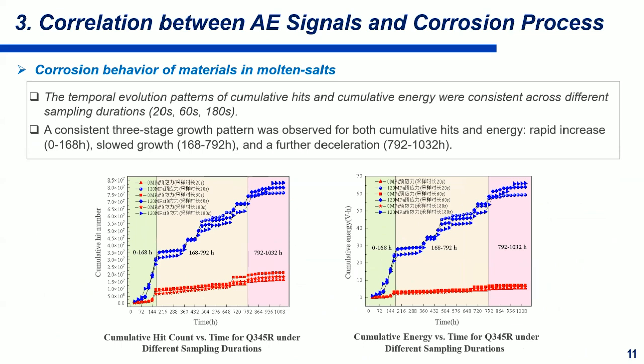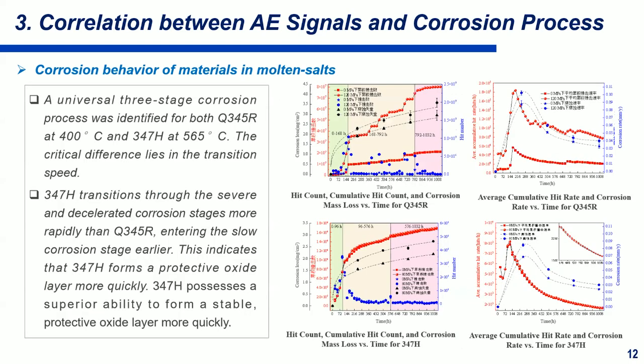The temporal evolution patterns of cumulative hits and cumulative energy were consistent across different sample durations, namely 20 seconds, 60 seconds, and 180 seconds. A consistent three-stage growth pattern was observed for both cumulative hits and energy: rapid increase, slow growth, and further deceleration, from 792 to 1032 hours.